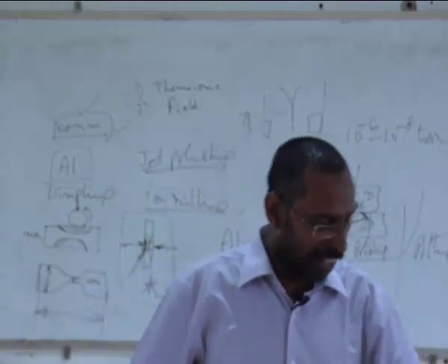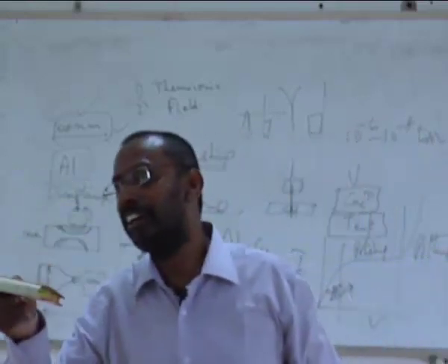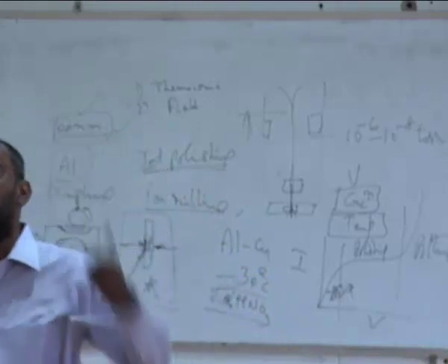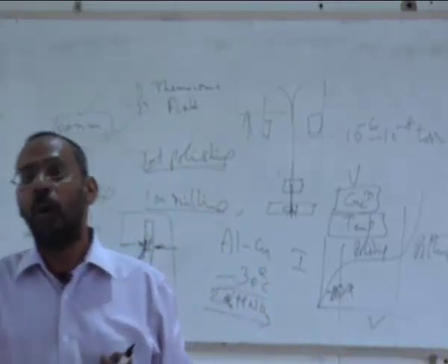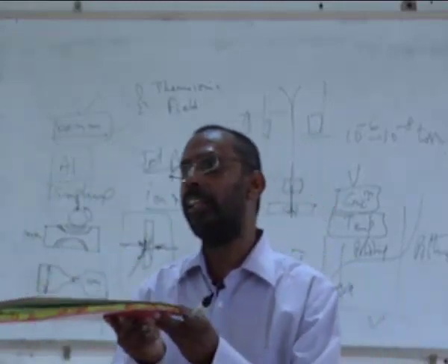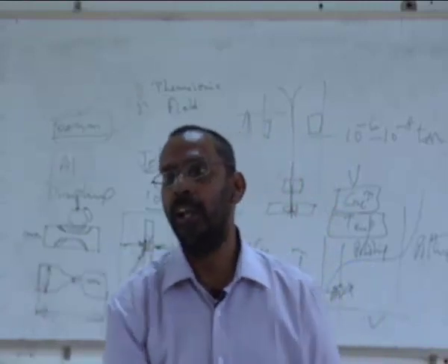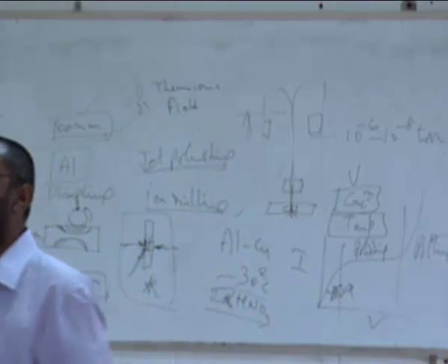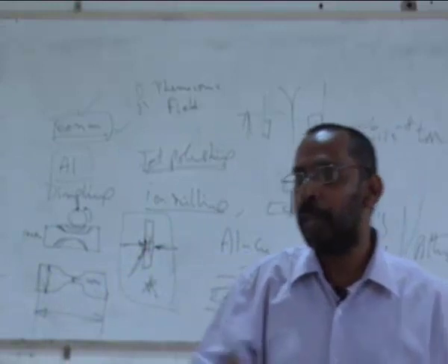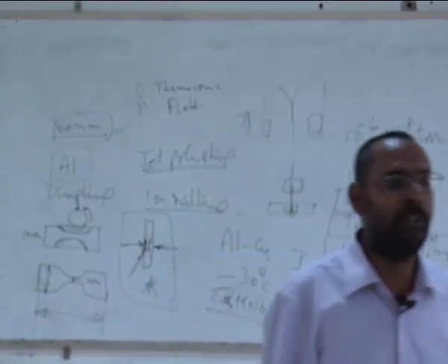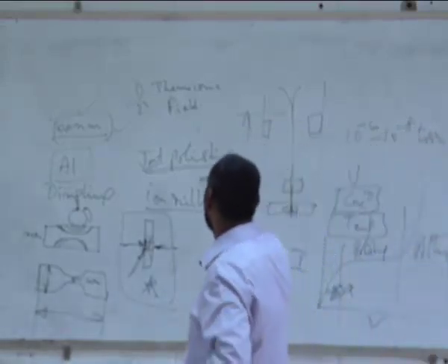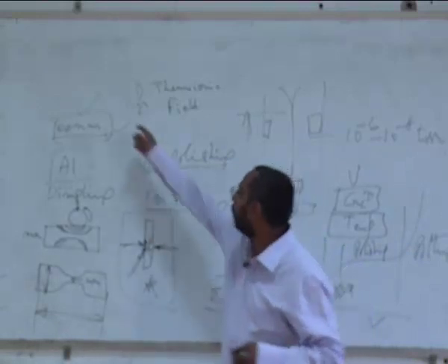So I am not seeing a big plate like this. I am actually seeing a small speck out of this plate. Let's say I have a rolled plate and I am taking only a speck out of it. How do I take that 3 millimeter disc? If I have a sheet like this, formed by slicing a sample, in this sheet I can use a punching machine. In metallic samples I can use a punching machine to punch. If you have ever seen papers being punched, a similar punch can be used to punch a 3 millimeter disc. And this 3 millimeter disc is allowed to go through jet polishing, finally to end up into this.